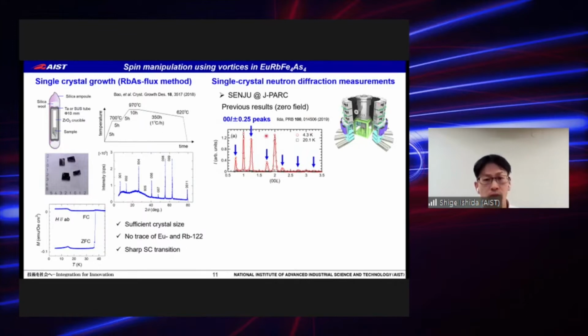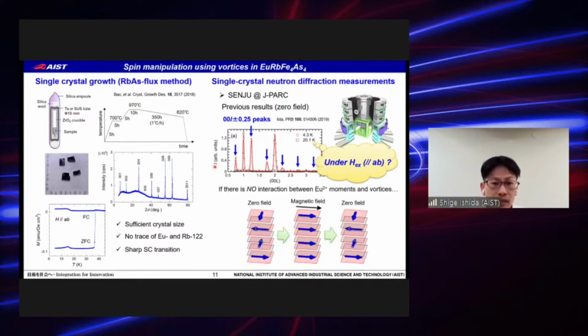In the previous study, we demonstrated the helical order at zero magnetic field, while in this work we applied magnetic field along the AB plane. So far it has been assumed that the magnetic structure of the europium moment behaves reversibly: by applying magnetic field, it reorients ferromagnetically, but by turning off the external field it returns to the original helical structure. So it is assumed that there is no significant interaction between the europium moment and vortices.